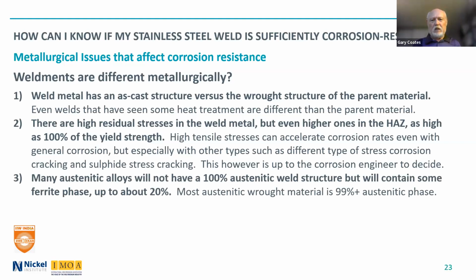Most austenitic alloys will not have a 100% austenitic weld structure. We design the composition of the filler metals to have ferrite in there a little bit, generally a minimum of 4. In some cases, it can be as high as 20, but usually between 4 and 12, I would say, is most typical, where the austenitic wrought material is 99% plus austenitic phase. 304, it may have a little bit of ferrite in there. 316L, almost nothing. And you can tell with a magnet sometimes if you have a plate, especially something thicker, that if you get a little bit of magnetic response, you have a little bit of ferrite there, but it's a very, very small amount.